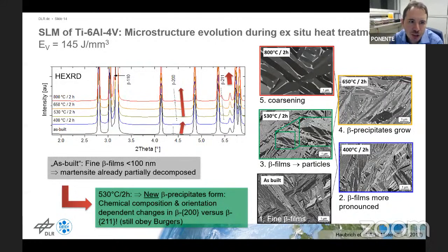Shown here are HE-XRD spectra, so XRD spectra taken at the synchrotron in Hamburg at DESY. And what you see here in the bottom is the 145 joule per cubic millimeter as-built state, where you see a very small signal for the beta phase, roughly 2%, and then going to higher heat treatment temperatures, 400, 530, 650, and 800 degrees Celsius for 2 hours each as an ex situ heat treatment in an oven of the material.